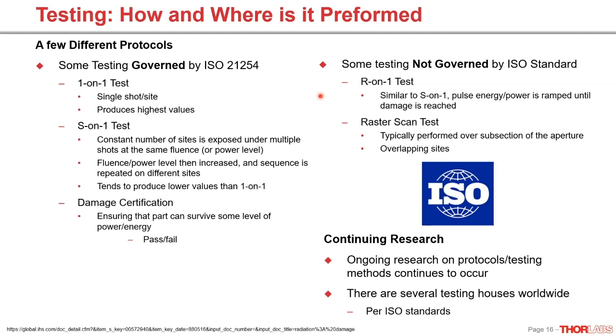The S-on-1 test addresses that particular drawback of the one-on-one test, because what it uses is a constant number of shots per site. Typically I've seen 10, 20, or 100. And this is multiple shots at the same fluence or power level. And then if no damage occurs, more sites are picked and the sequence is repeated at a higher fluence or power level. This tends to produce lower results than the one-on-one, but results that are probably more in line with how most users are using the parts.